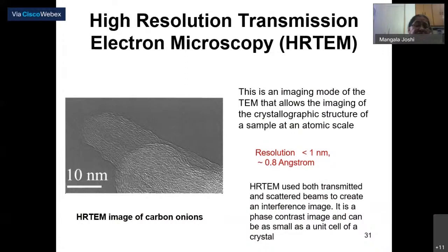Here the resolution can go less than 1 nanometer, about 0.8 angstrom. And HR-TEM uses both transmitted and scattered beams to create an interference image. It is a phase contrast image and can be as small as a unit cell of a crystal. You can see here an HR-TEM image of carbon onions. The scale you can see is 10 nanometers, so you can see less than 10 nanometers. So it is a very high resolution technique.